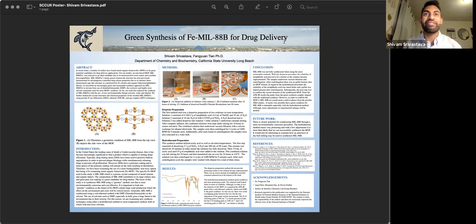So in this lab, we have been researching methods to use a more biodegradable and non-toxic option, and that would be an iron-containing metal organic framework, or an iron MOF. The specific MOF that we are studying in this experiment is MIL-88B, and it's a porous crystal that is composed of metal clusters and organic linkers. The composition of MIL-88B contributes largely to the surface area and great pore size. That makes it a good candidate for drug elution.